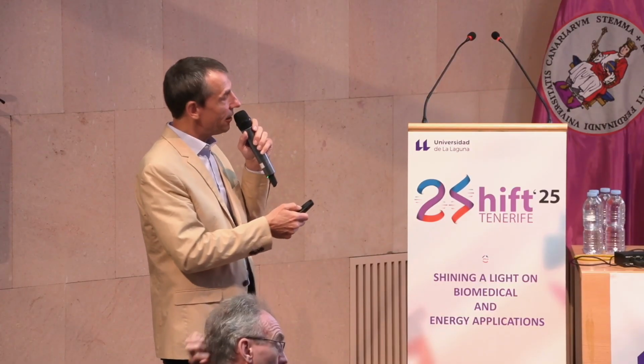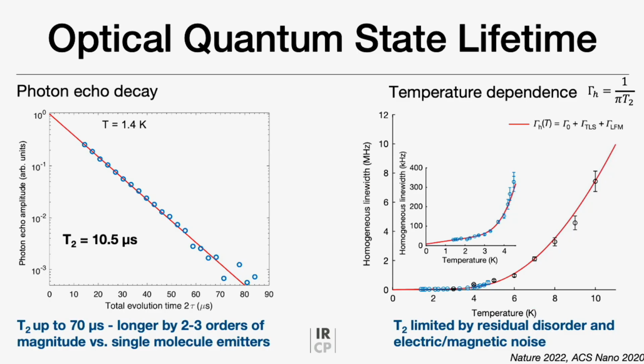An interesting question also is, okay, here we measure 70 microseconds. With ytterbium, we had more like 700 microseconds, and we were limited by the intrinsic lifetime of the excited state. Here, the excited state limit is 1 millisecond, so obviously 70 microseconds is very far from this limit. So what exactly is causing these extra perturbations to the transitions?